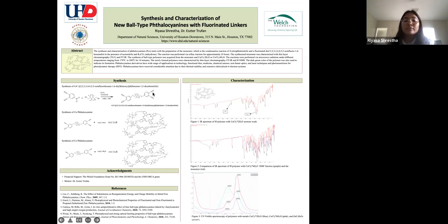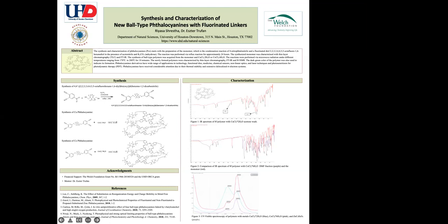So in the reaction, that bond will be consumed and a C=N double bond will show up. And these peaks over here in purple are the emergence of the C=N double bond, which can also be seen in the ball type here. So basically, we're looking for the reduction of this peak, and then the emergence of more of these peaks. I see. Thank you.